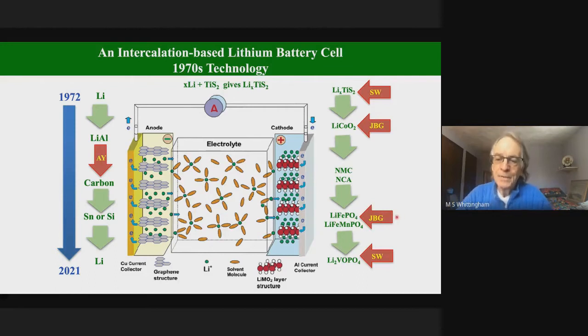John also came up a few years later with these phosphate materials. These are more stable, and it turns out the iron phosphate is a naturally occurring mineral. But the challenge here is this has much lower energy density because you're now carrying a heavy phosphate group with you. My colleagues are working on the manganese analog. This has a higher voltage and so may be advantageous. We are working on putting 2 lithium ions into phosphate structures in order to get the energy density back up to that of the layered oxides.